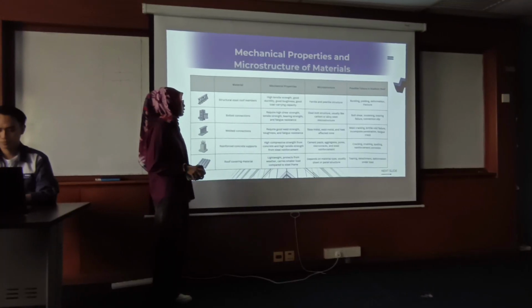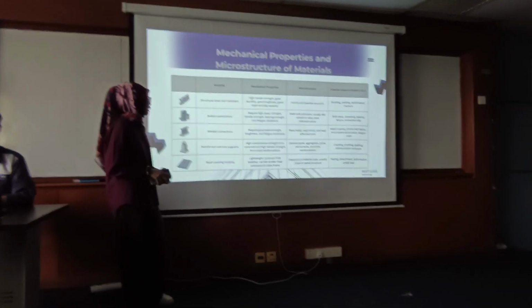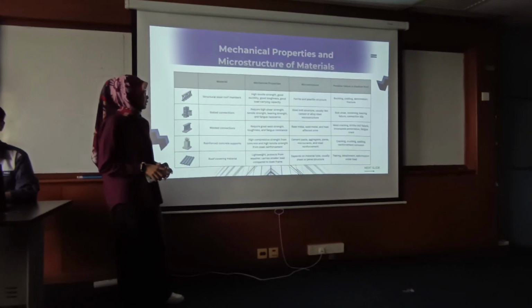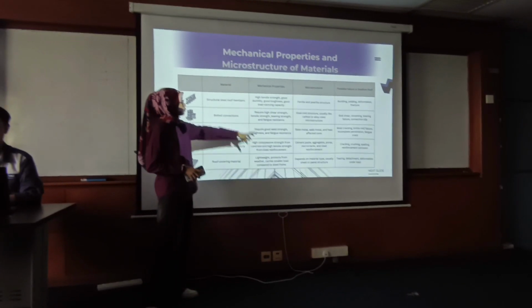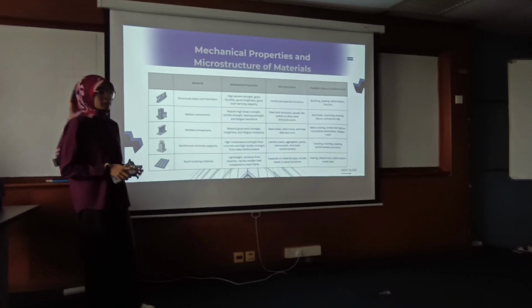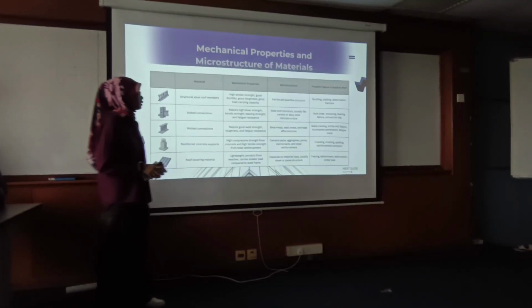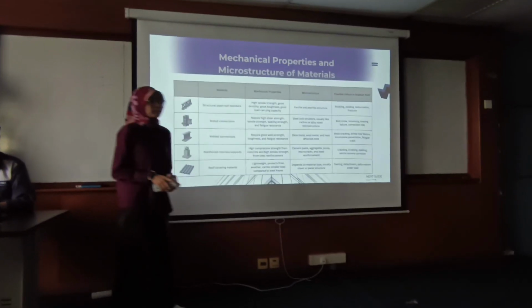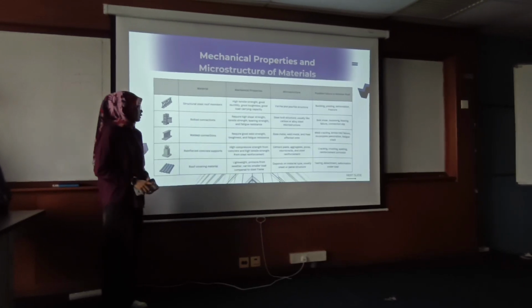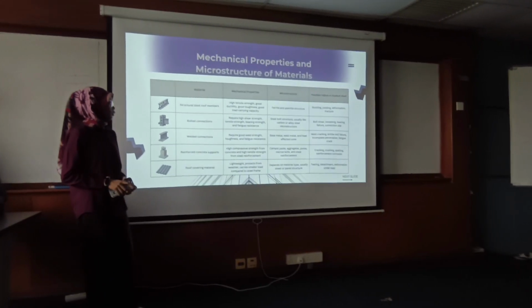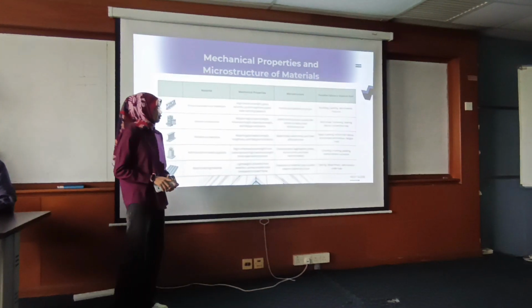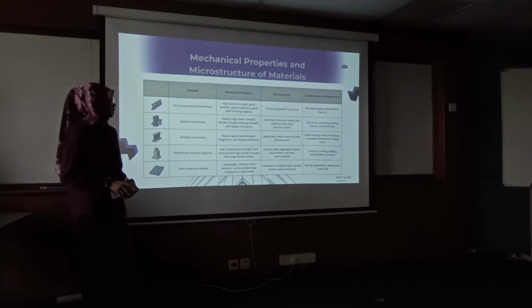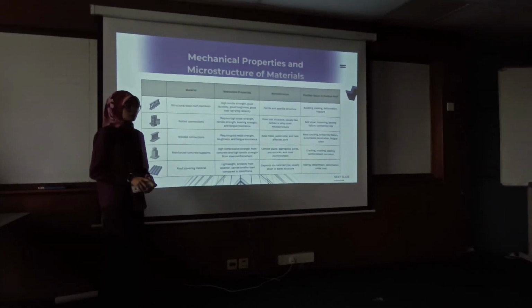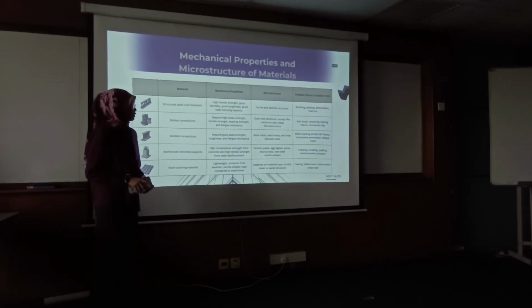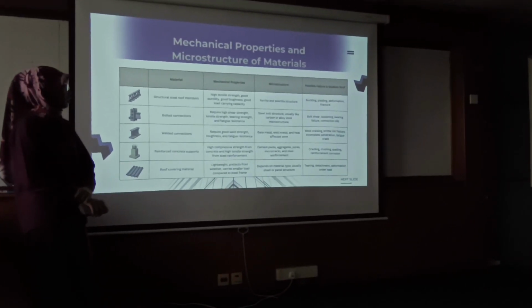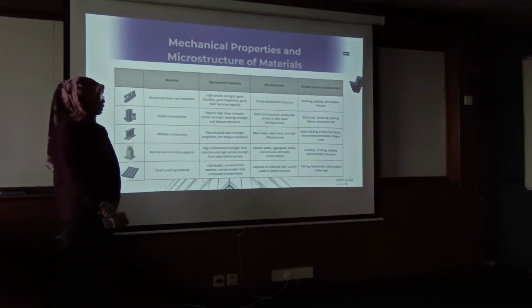For bolt connection, the mechanical properties required are high shear strength, tensile strength, bearing strength, and fatigue resistance. Steel bolt structure is usually carbon or alloy steel microstructure. Possible failures are bolt shear, loosening, bearing failure, and connection slip. Next is weld connection, which requires good weld strength, toughness, and fatigue resistance. For microstructure, base metal, weld metal, and heat affected zone. Possible failures are weld cracking, brittle fracture, incomplete penetration, and fatigue crack.